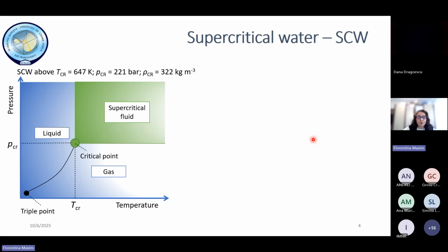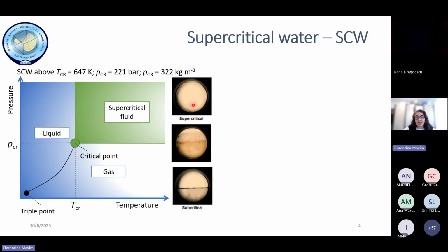The supercritical state of a fluid is considered the state in the pressure-temperature space at the end of the vaporization curve, when the liquid and the gas reach the same density, which is considered the critical density. For water, these are the values for the critical temperature, pressure, and density. There was a vivid debate on whether there is some phase transition in the supercritical region which can explain the drastic property changes, especially near the critical point, as the meniscus between the liquid and the gas, which is visible in the subcritical region, is no longer visible at the supercritical state.